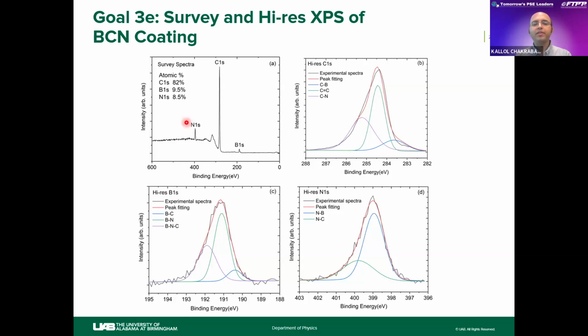Our next goal was to determine whether boron and carbon are bonded together so that we are truly getting a ternary BCN material. According to the high-resolution C1s spectra, we can see CB, CC, and CN bonding. Same thing for the high-resolution B1s—we see BC, BN, and most importantly the BNC bond in the high-resolution B1s, which is most important.